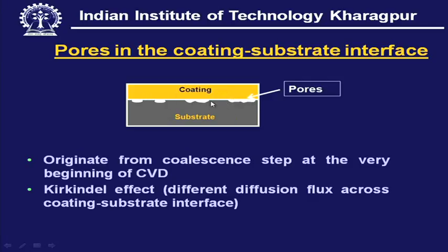will be supported by some bridge, and these are the places where we do not have any material, and that is just like a gap. So, under this condition, the area of contact between the coating and the substrate is not what should have been reasonable, and as a result, an external load can cause breakage of this coating, separation of this coating from this weakly jointed interface.